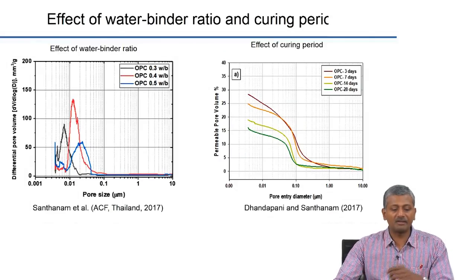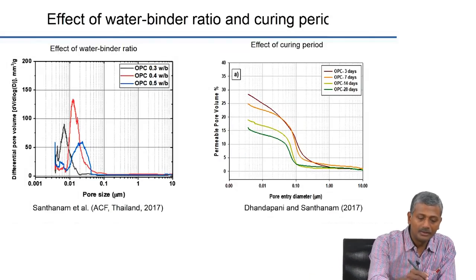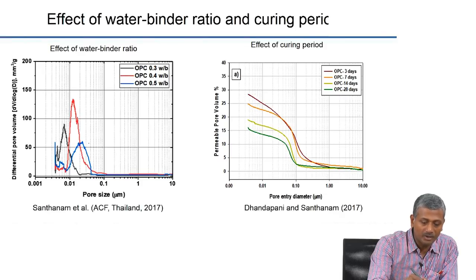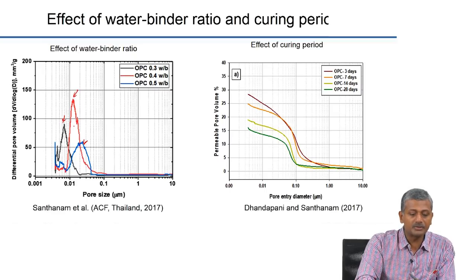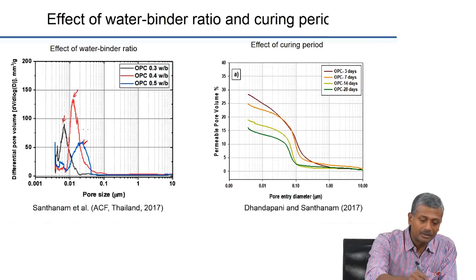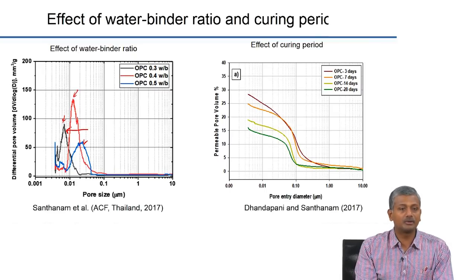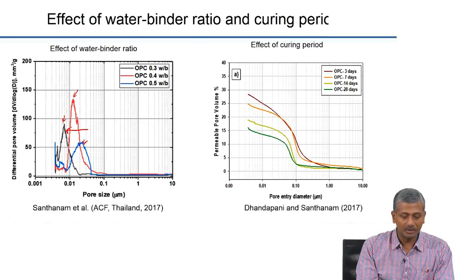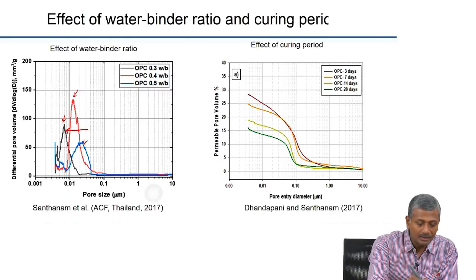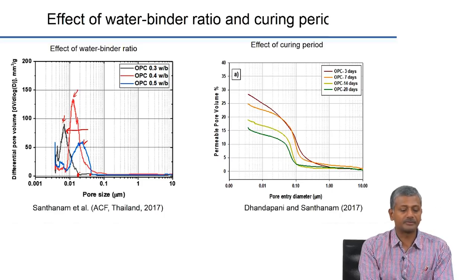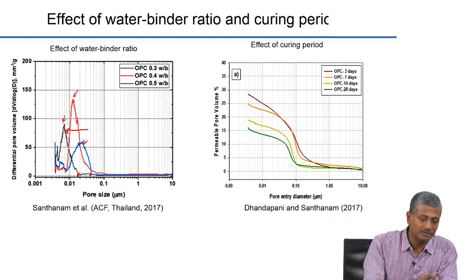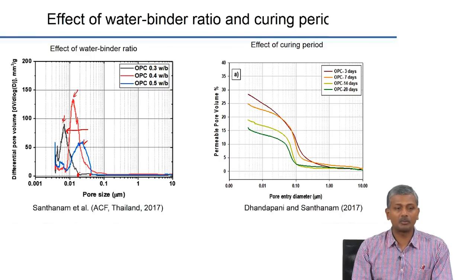So if you look at the effect of the water binder ratio, you see that the critical pore size is, this is 0.5 water binder ratio, this is 0.4 and that is 0.3. So as you are reducing the water binder ratio, your critical pore diameter is shifting to the left, that means it is reducing, okay. What you also see is the threshold diameter, right. You see that threshold diameter is here for the 0.5 system and here for the 0.3 system. So threshold diameter is also getting shifted to the left in the case of reducing the water binder ratio.